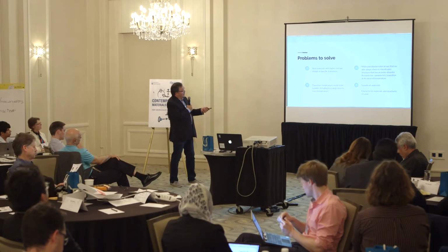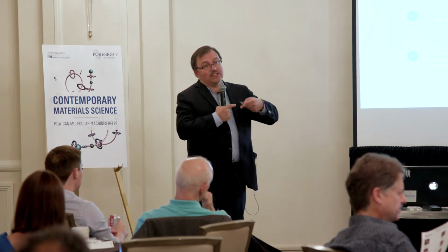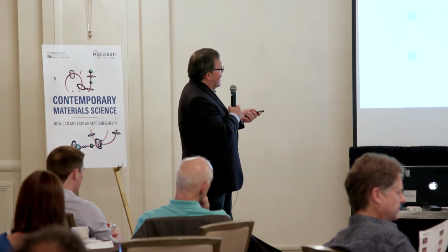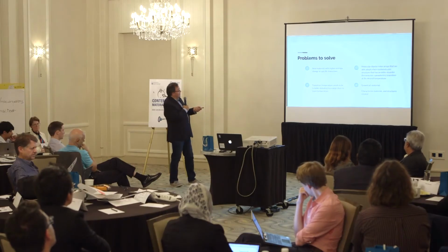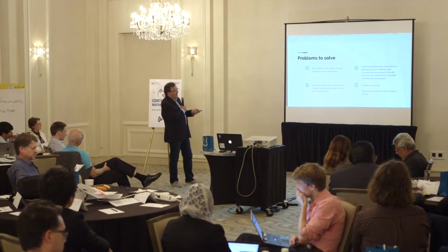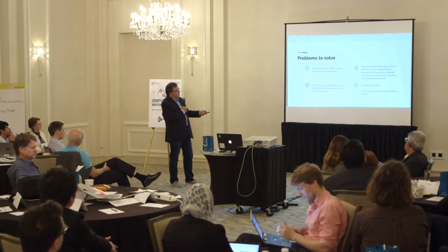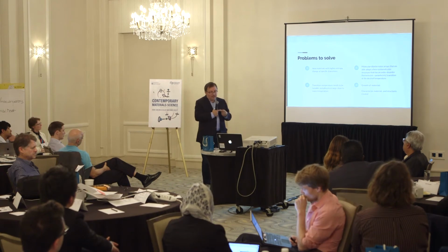We need molecular dipolar rotor arrays that are able to adopt a face-centered cubic structure. That is because that spontaneously will adopt the ferroelectric state and will give us the largest order-disorder effect, or ferroelectric-paraelectric transition. The transition temperature needs to be tunable. That can be done by tuning the distance between dipoles and the strength of the dipoles, right? Short distance, large dipoles, larger dipole-dipole interactions, larger energies, higher temperatures. We're going to have to grow the materials, prepare the materials, characterize them, and build the sort of epitaxially grown structure.